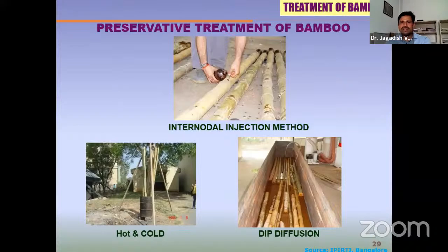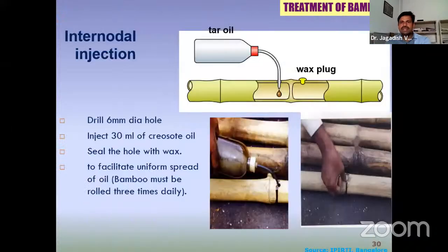One is the internodal injection method, wherein between two nodes, you drill a 6 mm diameter hole. Then you inject 25 to 30 ml of creosote oil and close it using wax, and then roll it so that the internal portion of the bamboo gets treated with the creosote oil. Creosote oil is a coal tar derivative. We treat the inside portion because there is a lot of starch material inside. Starch is food for insects.